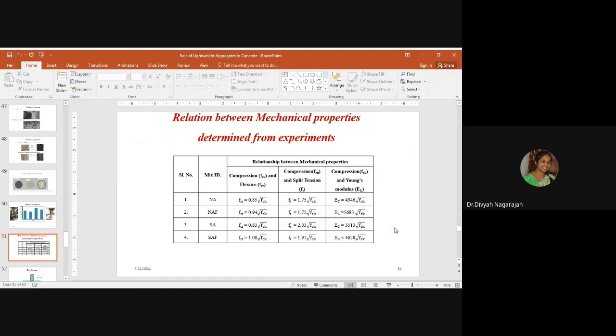As I said, the split and the flexural strength can be directly correlated with the compressive strength. It has a greater influence on the compressive strength. The relation between compression and split tensile strength for normal aggregate concrete is 1.75 root fck. When fiber is added, it reduced to 1.72 root fck. For sintered fly ash aggregate, it was 2.03 root fck, and it reduced to 1.97 root fck when fiber is added.